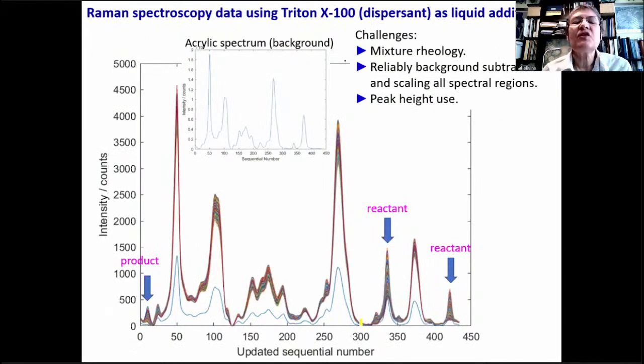So there are various challenges for these measurements, one of them to be fully quantitative. One of them is the rheology of the mixture, because this Diels Alder reaction may happen in one section of the reaction jar that is not accessible to the Raman laser. So we wanted to find an additive that could modify the rheology of the reaction so that the section of the jar that is illuminated by the laser would always have a rather uniform mixture of the reactants and the product.